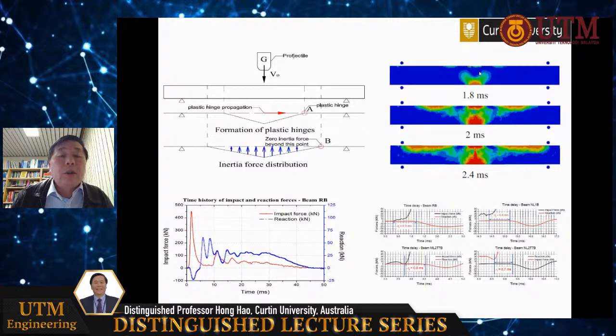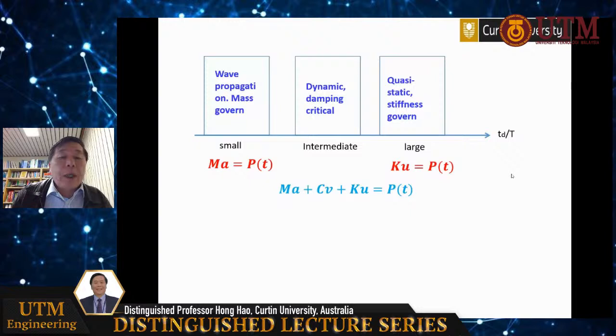Why do we get an active reaction force going down? Upon impact, the stress wave propagates inside the structure and reaches the top of the support first, so it generates an active reaction force. That is a common observation in impact tests. So when you do an impact test, you cannot use the load cell at the support to back-calculate the impact force, which will give you a wrong measurement.